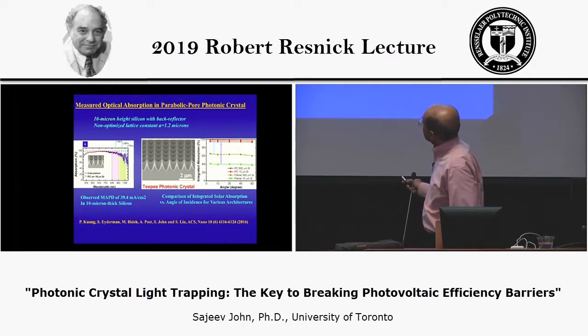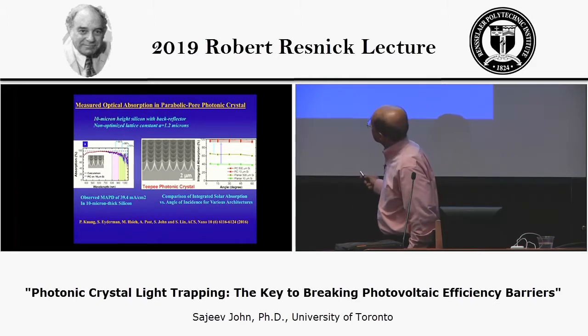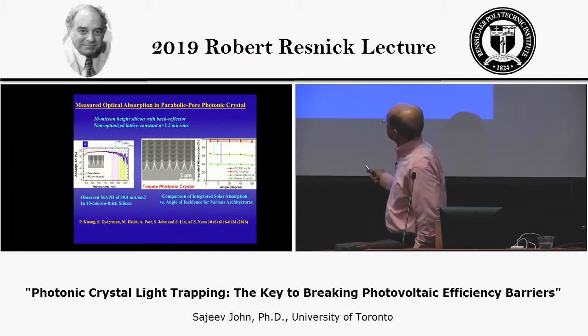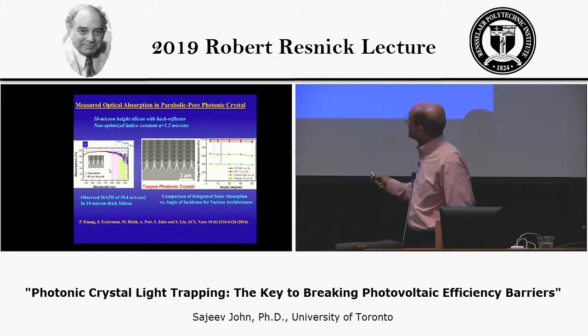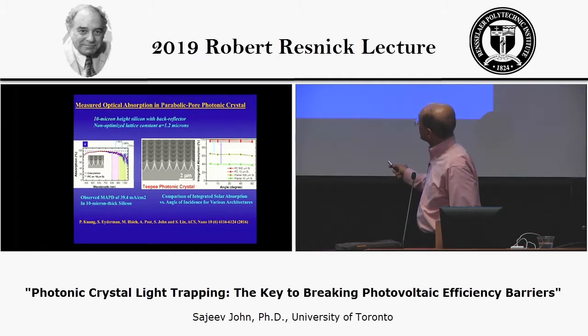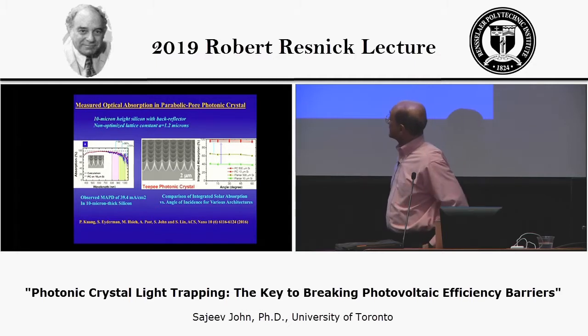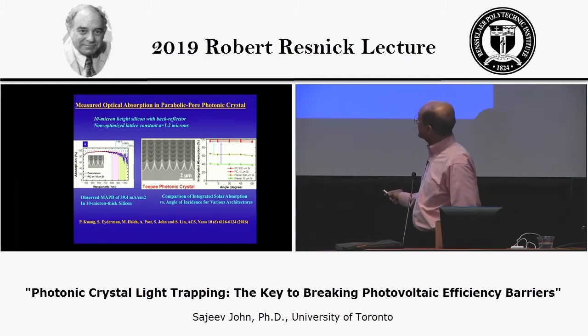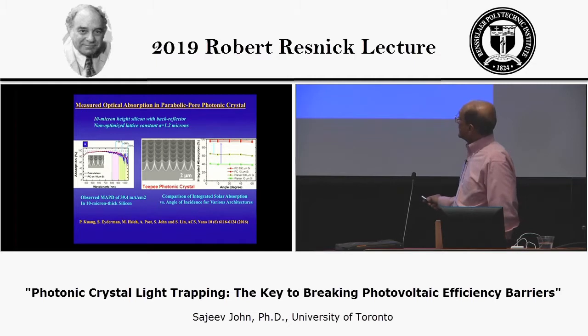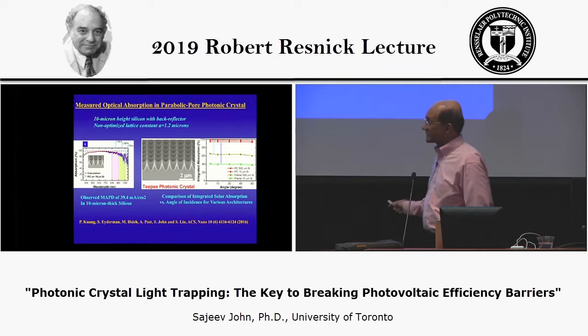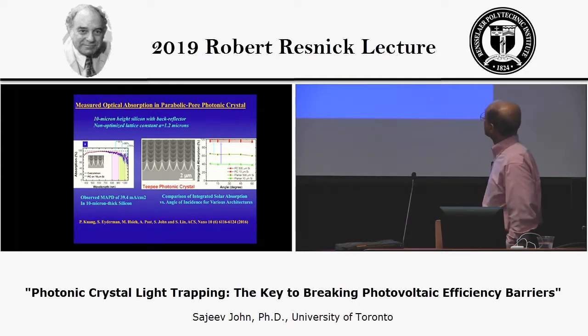The red curve is the experimental result, showing very high absorption even in this long wavelength regime. The blue curve is the theoretical calculation showing the resonance structures associated with it. Actually, the experiment averages over a lot of these resonances because it's over a broad area. But nevertheless, there's very good agreement. Here we observe and calculate maximum achievable photocurrent density of just under 40 milliamps per square centimeter.